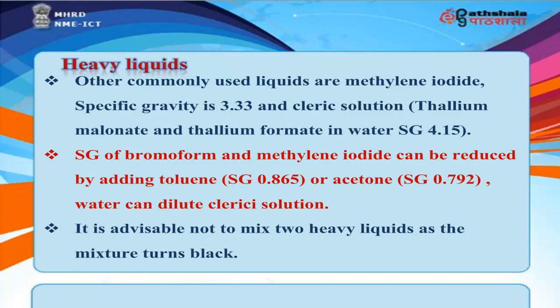Other commonly used liquids are methylene iodide, specific gravity 3.33, and Clerici solution, thallium malonate and thallium formate in water, specific gravity 4.15. The specific gravity of bromoform and methylene iodide can be reduced by adding toluene, specific gravity 0.865, or acetone, specific gravity 0.792. Water can dilute Clerici solution. It is advisable not to mix two heavy liquids, as the mixture turns black.